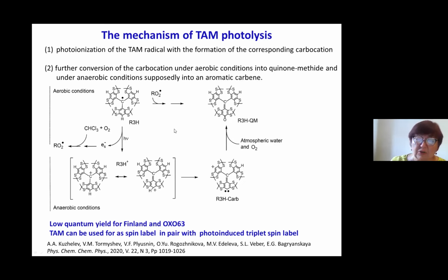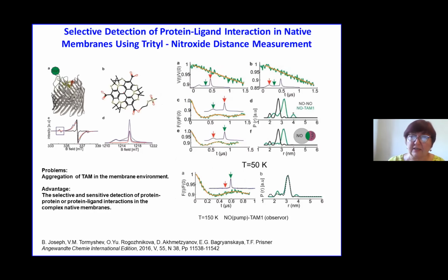oxygen. And this is very important, that trityls are not very reactive with reactive oxygen. And we use this information for future spin labeling of biomolecules. It's much better. In some cases, if we have formation of reactive oxygen species, for example, we have oxygen in some reductant, and then we have formation of reactive oxygen species, then the spin labeling has quite a low value. So we use it now for spin labeling of biomolecules using trityl radical. So we understood that trityl can be used as a good spin label.